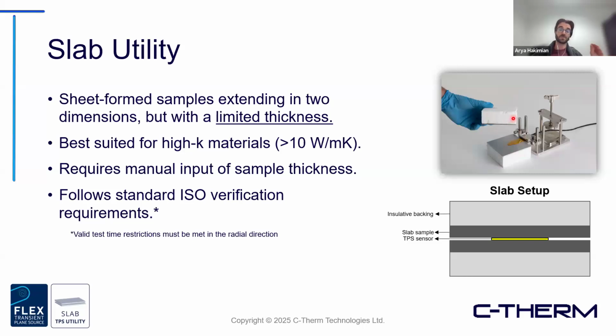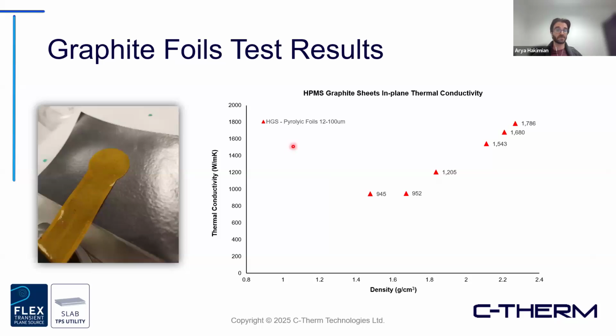Ultimately, this is for thinner, higher K materials, really designed for those above 10 watts per meter Kelvin, but with a thinner sample format. An example of this, we've shown this data before in previous webinars, is something like a pyrolytic graphite foil. This is something that we tested with the TPS slab utility, exhibiting some very high, almost 1800 watts per meter Kelvin in-plane thermal conductivities. So again, if you were primarily dealing with these types of materials, it would be more of a fit for the slab utility on Trident.